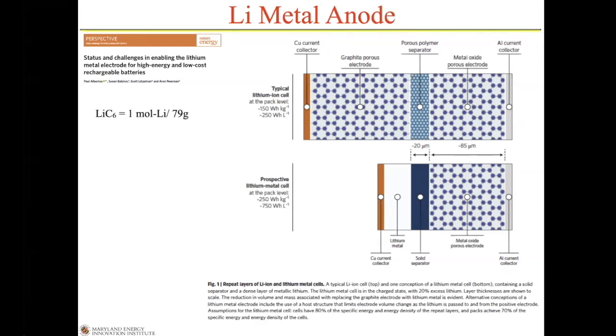One is the carbon anode that's typically there is actually a lithium carbon 6. And so if you take the mass of both the lithium and carbon, you get something on the order of about 339 amp hours per kilogram for the anode. But if you go to lithium metal, well, you get rid of the carbon. And the capacity goes to 3,861 amp hours per kilogram, basically a potential 10x reduction in anode mass. So I showed you the volumetric aspect. This is the mass aspect about why you would get better energy density by going to a lithium metal anode.